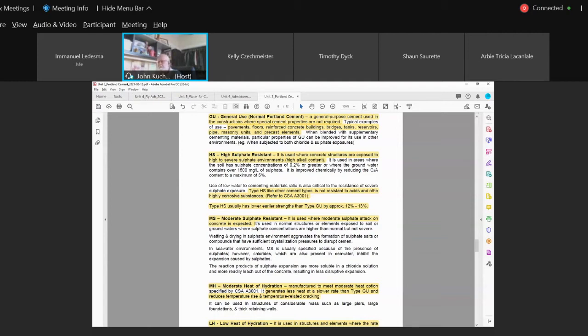Now sometimes we do a 1 day, a 2 day, or a 3 day, and that is done to sometimes say, can I put my structure into service? For example, can I open my pavements? I'm going to do a 3-day break. I cast on Friday and I'm going to test it on Monday. Can I put my pavements into service? Can I strip the forms? You're pouring grade beams, you're pouring walls, can you strip your forms? Can I start loading some loads onto my structure? Can I start putting some strength bearing elements onto my pile caps? So a couple of reasons: stripping forms, putting things into service, and to predict, are my 28 days going to make it?